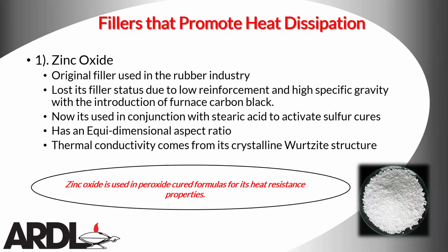And as I mentioned, most people think, well, zinc oxide's just an activator, and it was a filler a long time ago. But I've been in the rubber industry for 29 years, and one thing I can tell you is that every peroxide cured compound I have ever seen has zinc oxide in it. And you have to wonder why, because you do not need zinc oxide to activate a peroxide cure. It's only going to activate a sulfur cure. The reason that zinc oxide is in there is because it's going to improve heat resistance, and it does that through thermal conductivity.